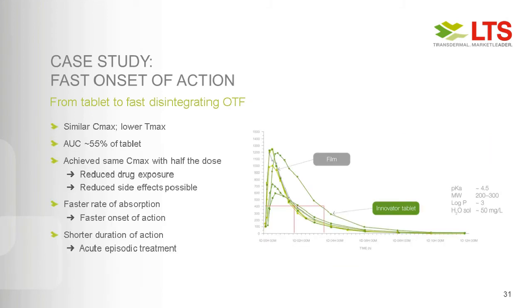So overall, this case study from moving to a tablet to an oral thin film allowed us really to have the similar Cmax as said before, but at a much lower Tmax, so faster onset of action. AUC with 50% of the dosing was about 55% of the tablet, so we can achieve the same Cmax as said before with half the dose. We can reduce drug exposure and also possible side effects which come along with the drug exposure.